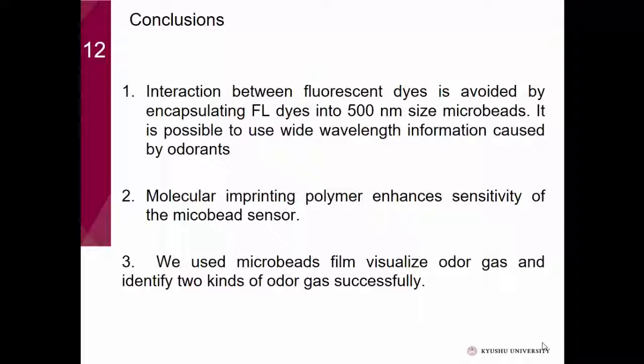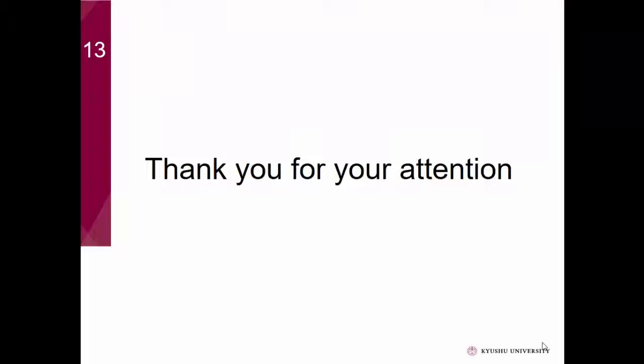In conclusion, the interaction between fluorescent dyes is avoided by encapsulating each fluorescent dye into approximately 500 nanometer-sized microbeads, and it is possible to use wide wavelength information caused by odorants. The second conclusion is that molecular imprinting polymer enhances the sensitivity of our sensors. We can use these microbead film sensors to visualize odor gas, and can even successfully identify two kinds of odor gases. Thank you for your attention.